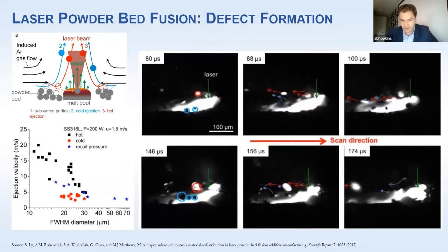So, defect formation. What's going on here? I'll start in this top left diagram. You have this melt pool, and you have metal vapor being created by the laser. The laser skin depth on these particles is on the order of a few tens of nanometers, or even a handful of nanometers. So very, very quickly you are vaporizing components of the metal particles, and they are blasting out of the way.